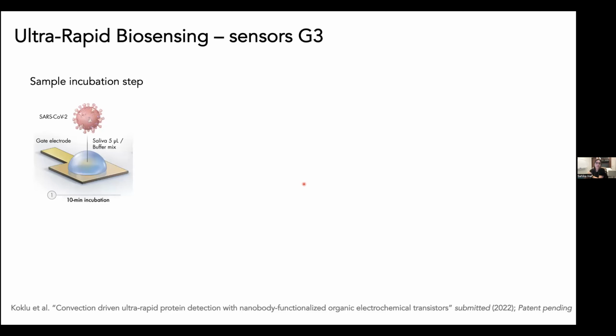Another area where we improved is the sample incubation step. Initially, I was telling you that we were putting the patient sample on the gate electrode surface and leaving it for 10 minutes there. To improve the mixing a bit, we were doing a few pipetting steps in and out to increase the diffusion of the virus and the viral proteins to the sensor surface. But this step is not optimized and it can cause a lot of error and sample-to-sample variation.